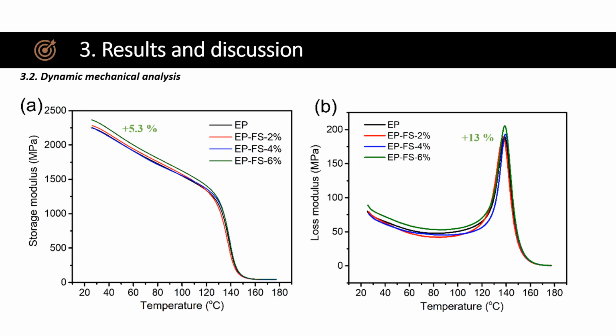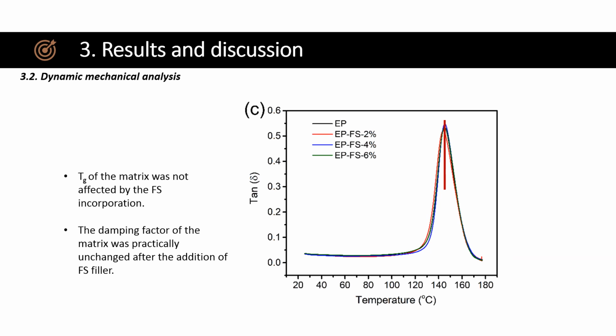Through dynamic mechanical analysis, the storage modulus, as seen in figure A, and the loss modulus, as seen in figure B, can be obtained. It is observed that for the composite with the highest amount of reinforcement, corresponding to the 6% in mass of the ferrotitaniferous sands, there is an increase in storage modulus of 5.3% and in loss modulus of 13%. Also through dynamic mechanical analysis, the tan delta curve can be obtained. As you can see, the glass transition temperature of the matrix was not affected by the incorporation of the ferrotitaniferous sands. Also, the damping factor of the matrix was practically unchanged after the addition of the filler.